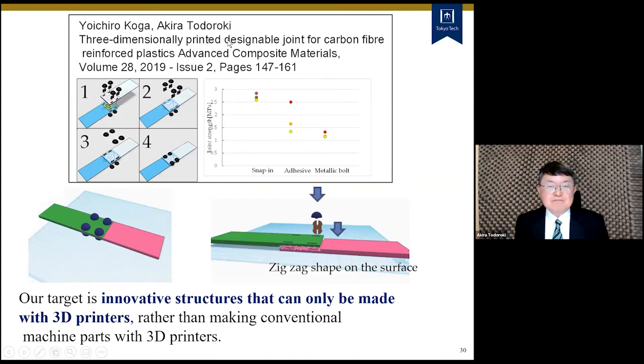This slide shows that we started to make a special joint. It has high strength and high reliability. This result is joint strength. The ordinate is joint strength, and if we use adhesive, the strength itself is very high in some cases, but in some cases it has low strength. So the reliability of the adhesive joint is very low. And if we use a metallic bolt, the data scatter is very small, so the reliability is very high, but the strength itself is very low.